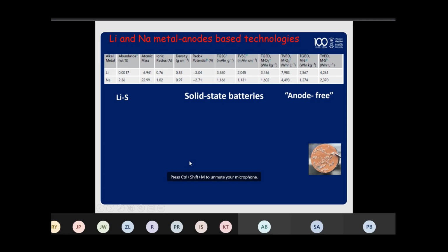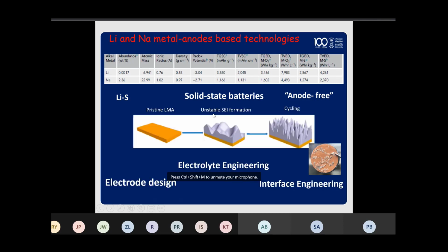However, the future, and I'm conscious of time, so I will go through this briefly. The real future is in enabling the use of lithium and sodium metals as anodes, exactly in the same way as we saw for lithium-sulfur. Goodenough, the father of lithium-ion batteries, actually considered implementing such anodes as really the holy grail. This is because of the high energy densities, of course, and the lowest possible redox potential, which means that I can really increase the operating voltage of the batteries, increasing energy density.